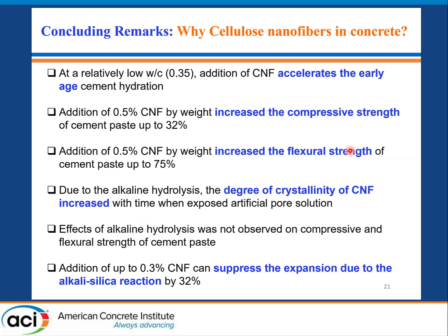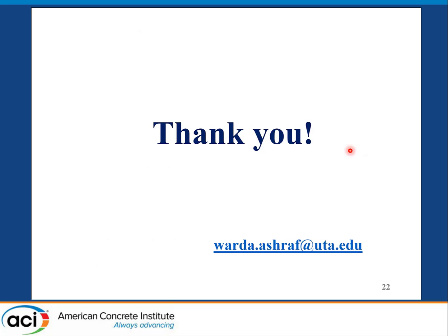In conclusion, why cellulose nanofibers in concrete? First, it can accelerate early-age cement hydration due to a nucleation effect. It can enhance compressive strength at later ages, and as a fiber it can also improve flexural strength. Cellulose nanofiber does experience alkaline hydrolysis, but we did not observe any significant negative effect on strength — strength was still increasing. And this alkaline degradation can actually be used to our benefit to suppress alkali-silica reaction in mortar systems. Thank you very much.